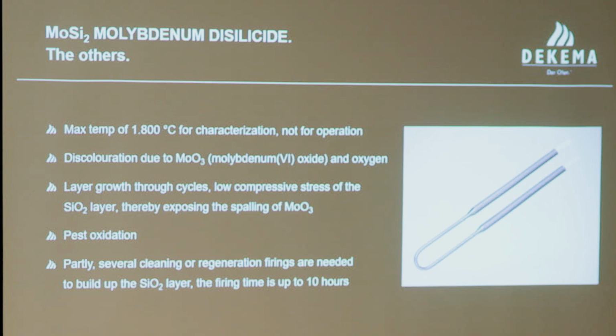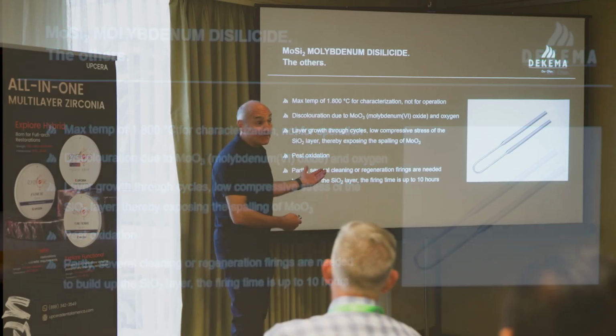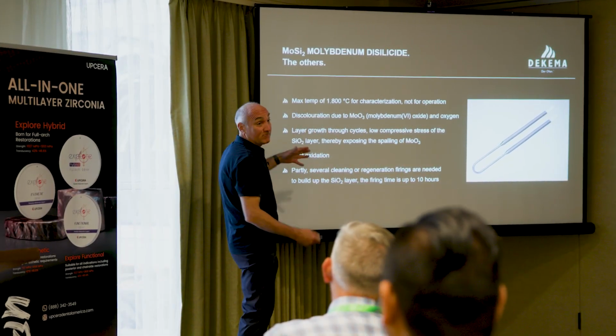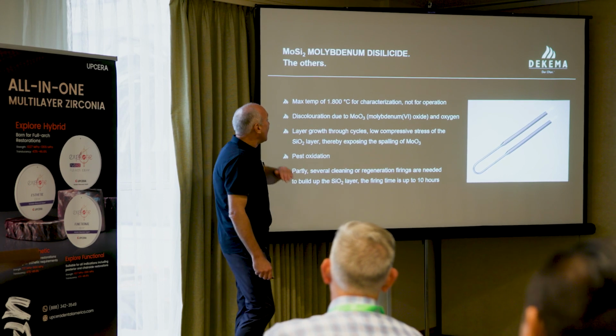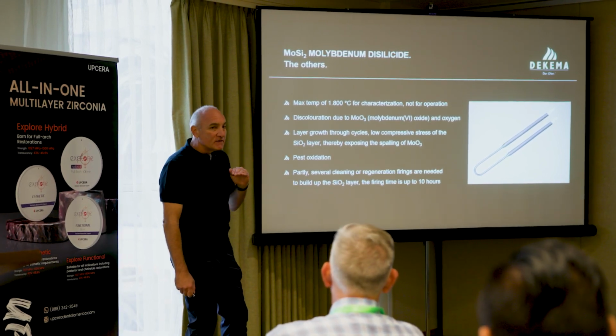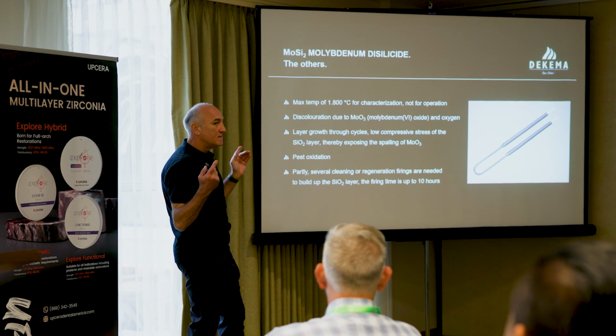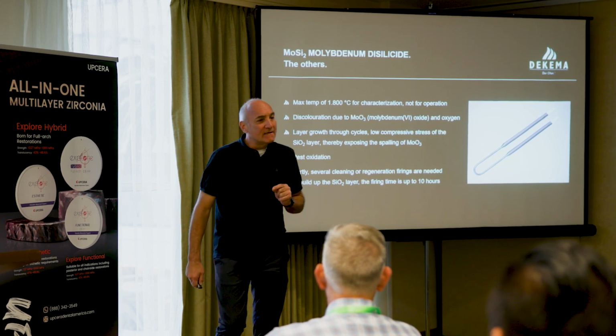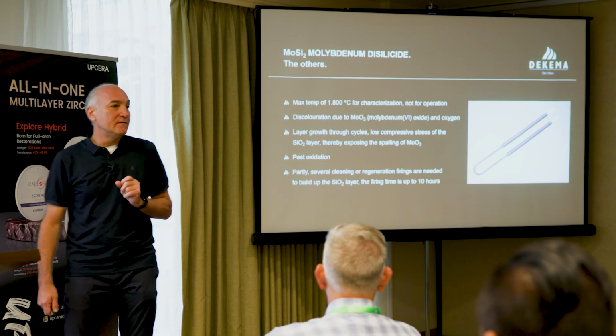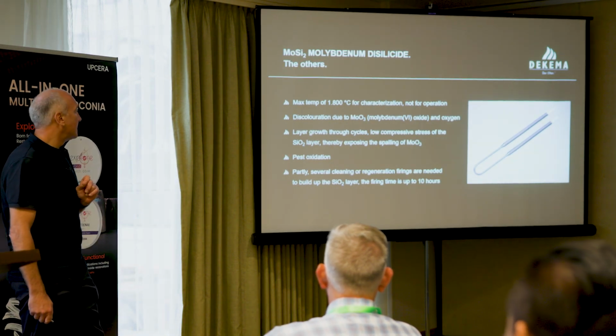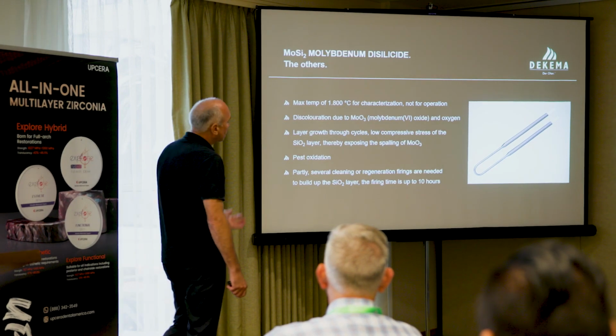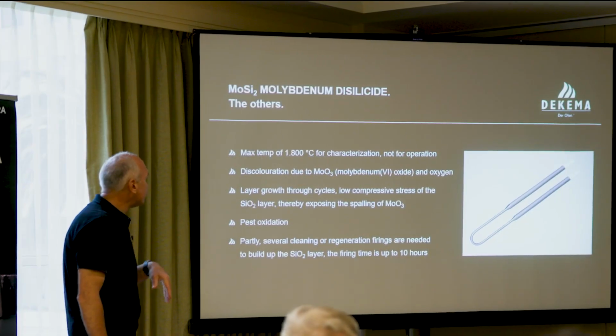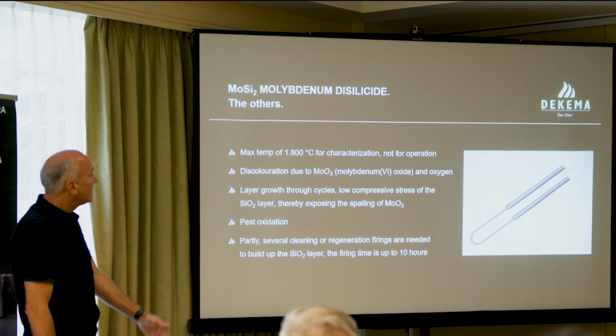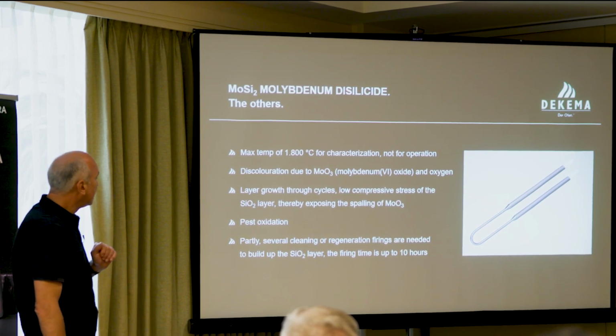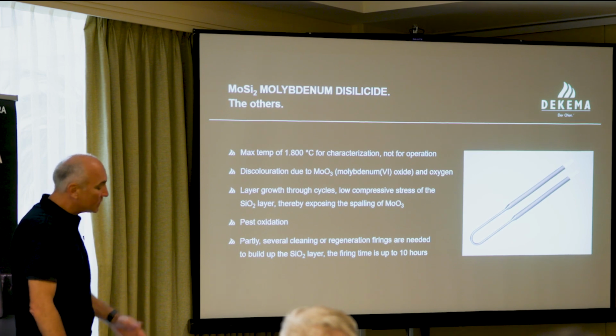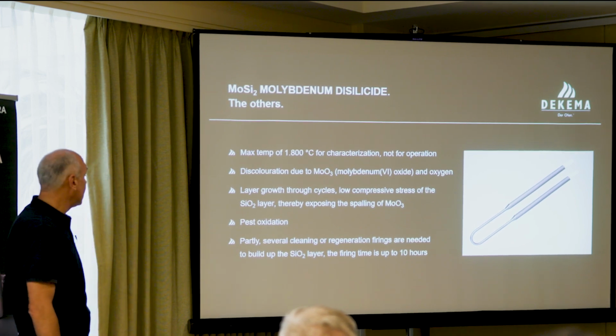Okay, so summarizing up again. As I told you, I didn't know the slides before, but now we can summarize it. It's a characterization temperature, not an operation temperature, what they talk about when they talk about 1800 degrees. And what do you need an 1800 degree heating element for? Zirconia. Discoloration because of rare earth, molybdenum trioxide, and so on. Layer growth, meaning you need glass.